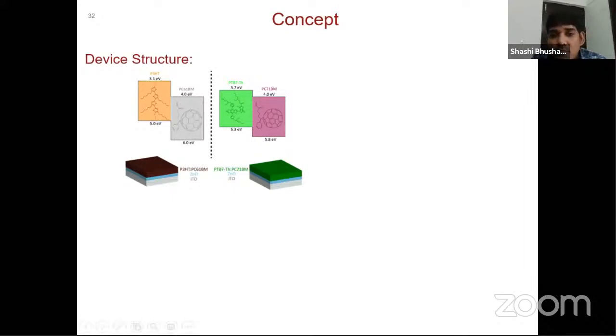And this material in the solar cell community has a VOC, open circuit voltage, of 0.7 to 0.8 volt, and P3HT has a VOC of 0.5 to 0.55 volt. So obviously it has an increased open circuit voltage.